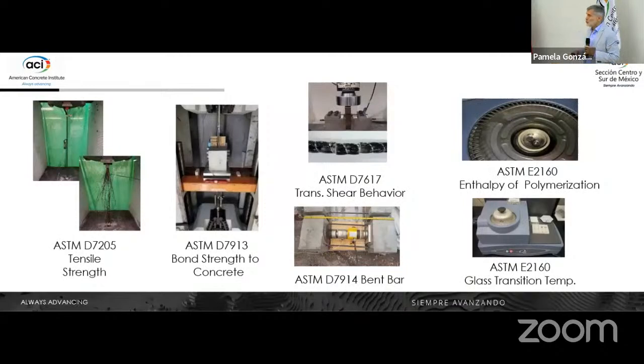In order to make sure that these elements are compliant with the code, we run a series of different tests, and I list some of them. Some of them may not be familiar to civil engineers, like enthalpy of polymerization. What does that mean? Well, in very simple words, if you're baking a cake, you want to make sure that it's cooked. And this is the enthalpy of polymerization. Because if the polymer is not fully polymerized, then it will absorb water and you will lose the durability that otherwise you would have with the proper cure.